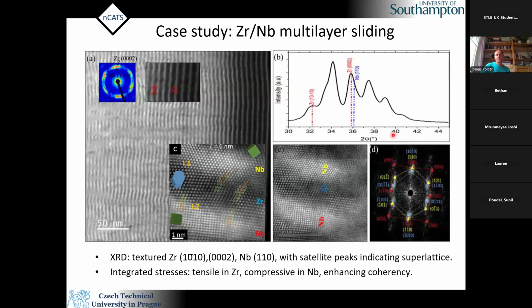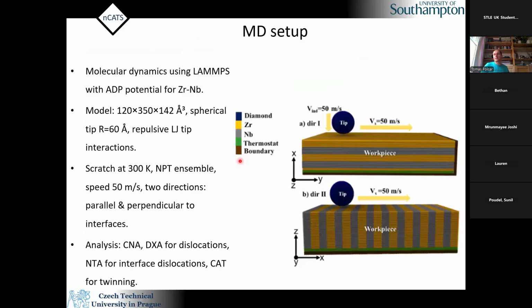Okay, another thing to show in tribology is how you can really connect other areas with tribology. I mentioned that I was invited to this European project on interfaces resistant to neutron damage, basically nuclear science. So we produced these multilayers. You can see this is a very, very thin multilayer coating with something like 3 nanometers of zirconium and 3 nanometers of niobium. Very, very thin multilayer, because you are interested in interfaces. I will not say anything about the neutron damage or helium bubbles growing there, but I will show you tribology, because we had everything, and when we studied everything, I said, why not study tribology as well?